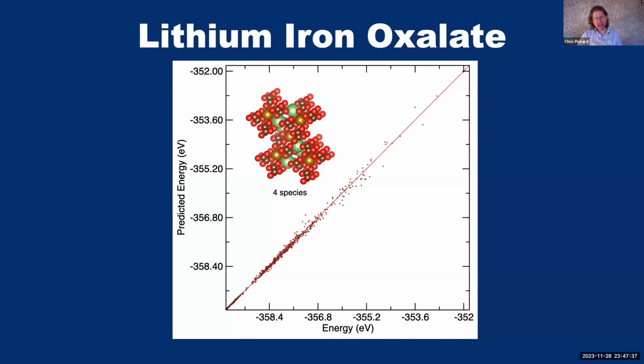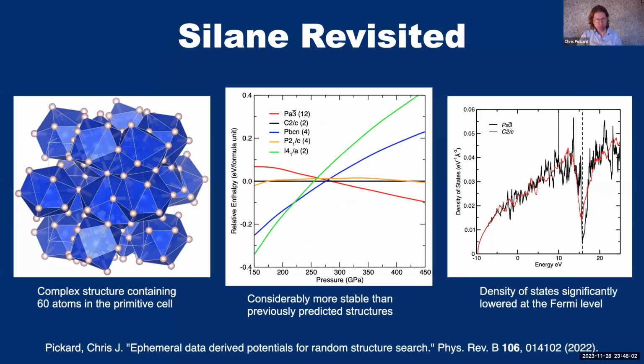And the reason we tolerate that is that very rarely are we actually interested in those very high configurations, but we want the energy landscape to be roughly right at these high energies, so that when we do a random structure search, it moves away from those high energy parts towards lower energy regions. If we hadn't described those higher energy parts of the energy landscape, maybe it could easily get trapped in a very deep local minimum, which would hinder any searching.